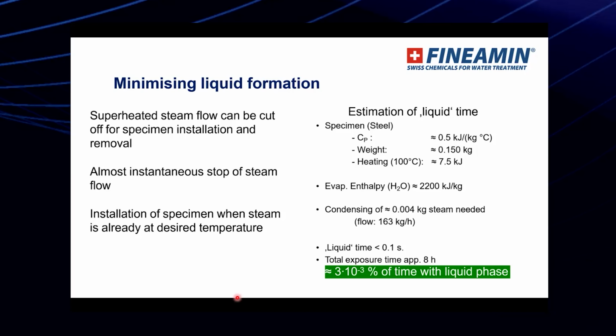So in this case, the condensation enthalpy is around 2,200 kilojoules per kilogram. So around 4 grams of steam needs to be condensed. And then with the steam flow around 163 kilograms per hour, we calculate the liquid time is very, very small. I would say it's pretty insignificant. It's less than 0.1 seconds.